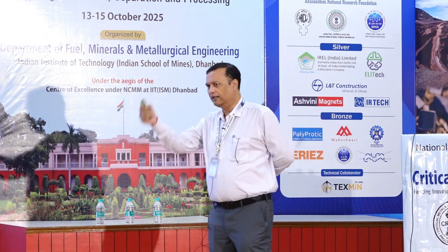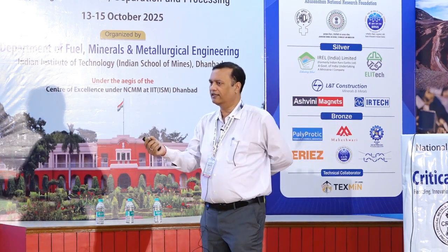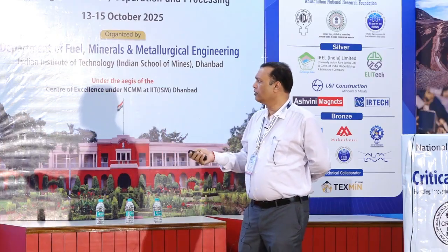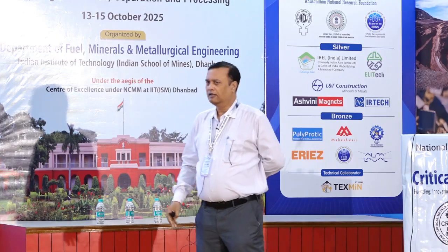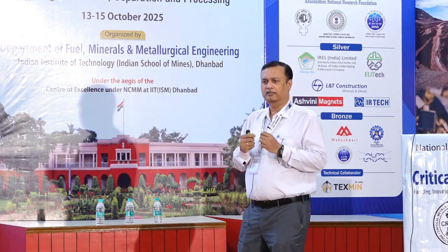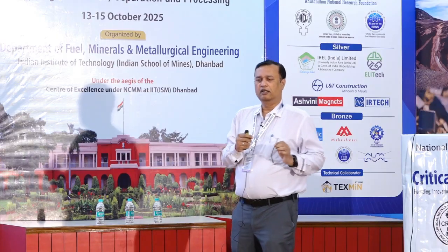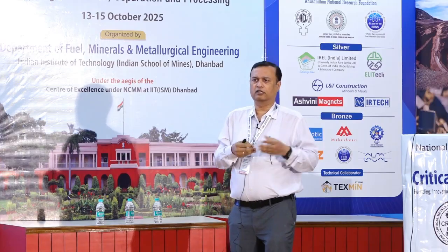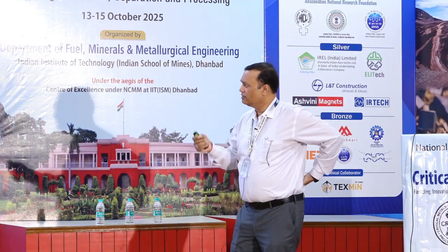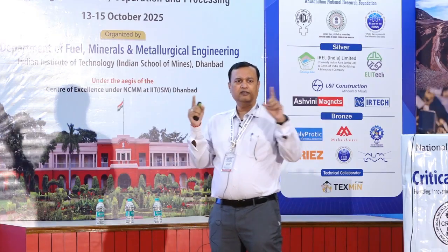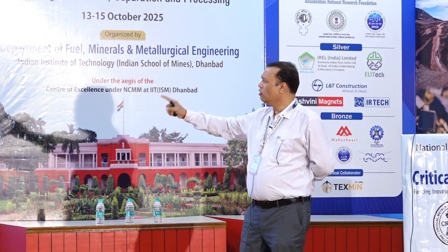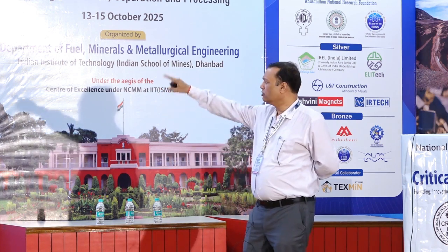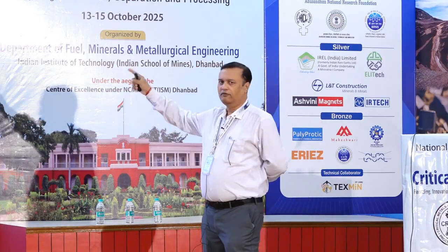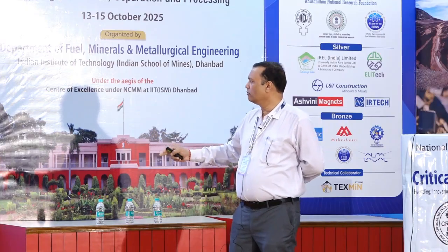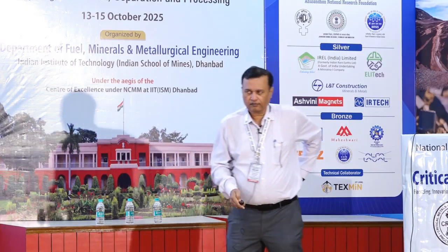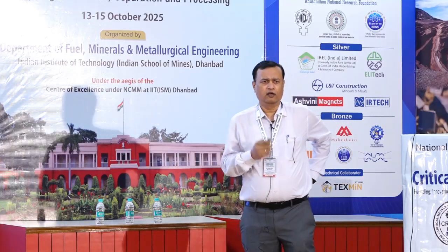One way is to reduce the particle size, or the grain size, and when we reduce the grain size, it is reported in the literature that the coercivity of the magnet increases. But when we reduce the grain size of NdFeB magnet, there is a challenge: because of its highly reactive nature, this powder immediately oxidizes, or sometimes it can catch fire also. Therefore, to process this magnet with very fine particle size, we need special setups for pressing, orientation and the whole magnet making process. It has to be done under inert atmosphere, and this kind of setup we have already established at DMRL, and with this we are able to produce 42 grade NdFeB magnets. And this has a Dy content of less than 1 weight percent.